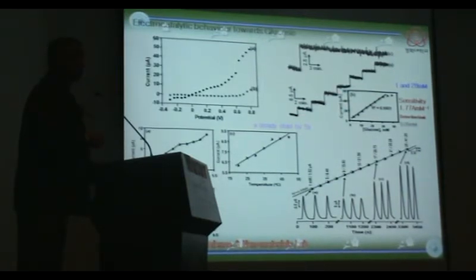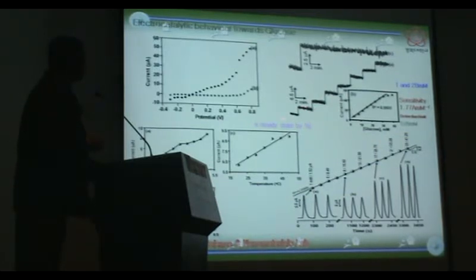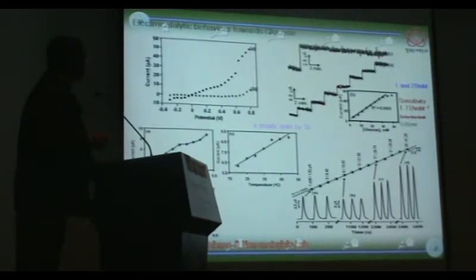We also tested the amperometric response of the electrode, and by just injecting glucose, a sudden change in the current can be seen, and it reaches a steady value within 5 seconds. This response is very fast, and it gives steadily increasing current values with increasing concentration of glucose.